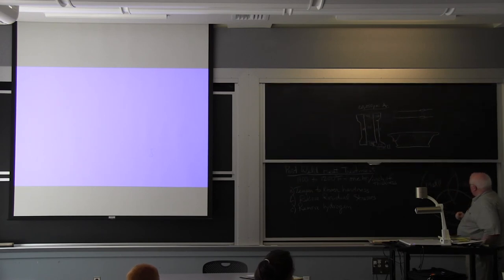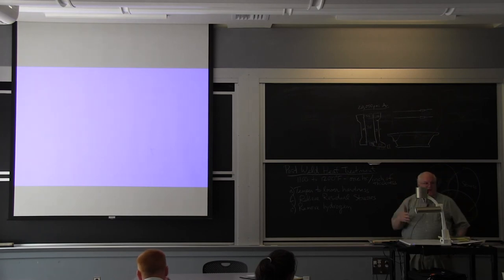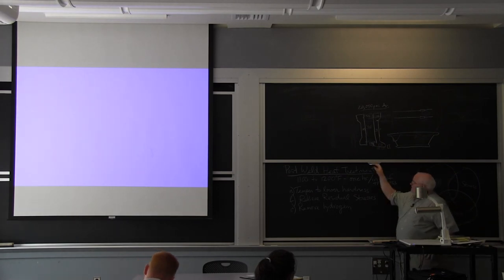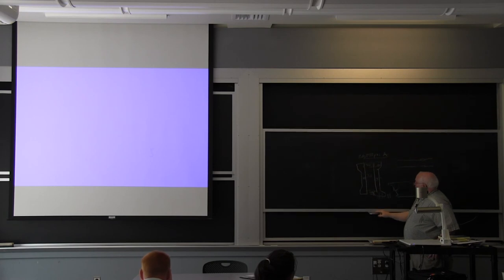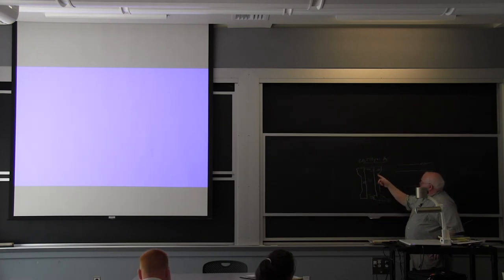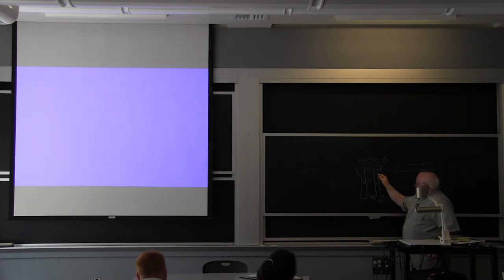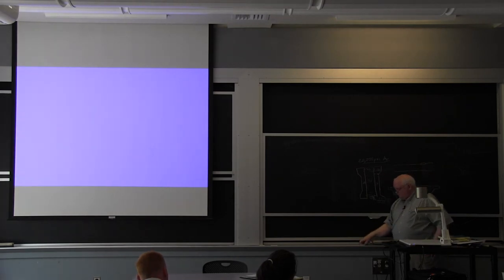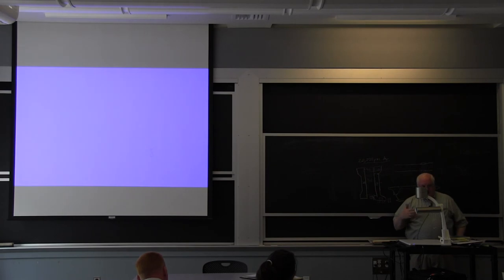You can shrink this circle. The stress, well, they had calculated the stresses at steady state when this thing was operating. And in steady state when this thing is operating, you should actually have your maximum tensile stress on the inside, depending on where the heat zone is, but it was on the inside. In fact, the crack had started on the outside, and I remember coming back from that second day when I actually got to see the piece.